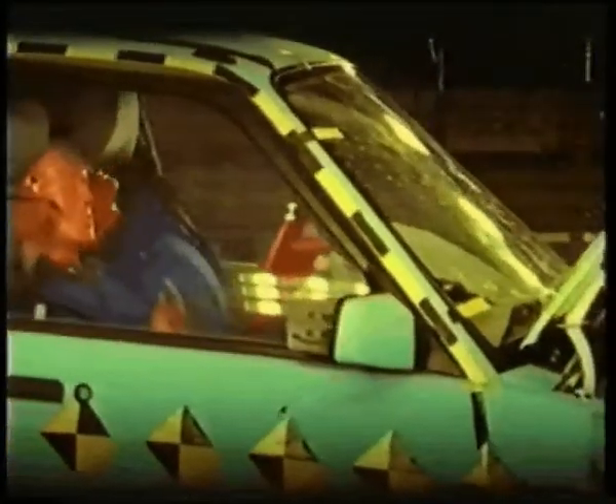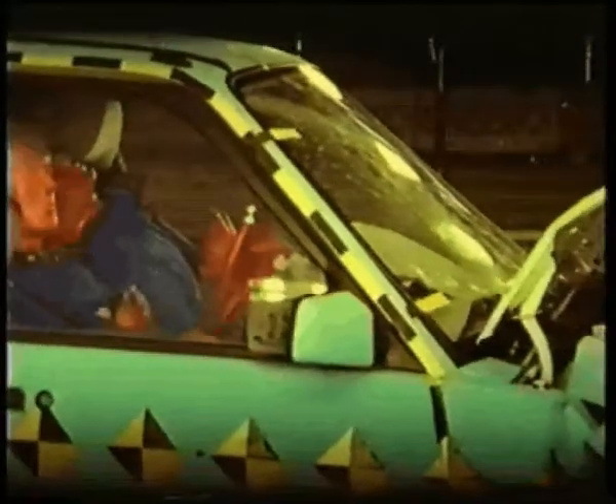This film, shot at 1,000 frames per second, shows the degree of screen movement. The sudden deceleration on impact resulted in considerable damage to the vehicle, not to mention having a devastating effect on the dummies which had been placed in the car to simulate the driver and passenger. However, the screen exhibited only slight movement due to the elasticity of the bonding material, and such elasticity was well within the design specification.